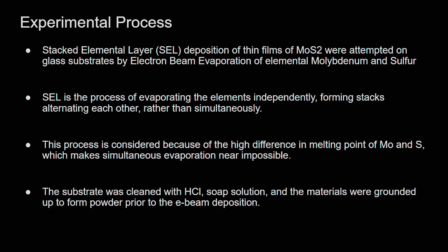Stacked elemental layer deposition, SEL for short, of thin films of MoS2 were attempted on glass substrate by electron beam evaporation of elemental molybdenum and sulfur. SEL is the process of evaporating the elements independently, forming stacks alternating each other, rather than simultaneous evaporation.